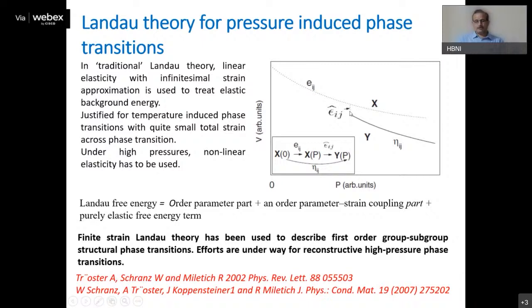For example, let us consider first order phase transition. In case of the first order phase transition, we have some transformational strain. So there is some strain which corresponds to this transformation of the phase to this phase. And then again, the second phase follows some equation of state. So in case of high pressures, if you consider total strain, it will have two parts. One is the elastic strain part of the initial phase, and then we have the transformational strain, which is a spontaneous strain, plus some strain corresponding to the equation of state of the second phase.